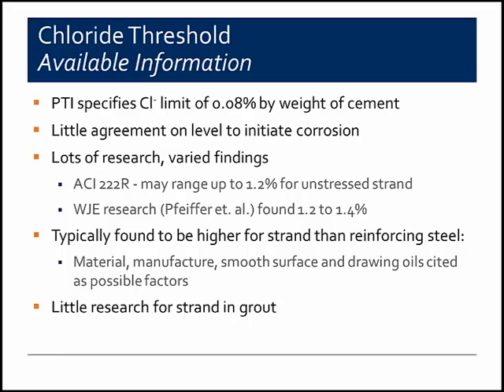In general, the chloride content threshold for strand has been found to be higher than that for reinforcing steel. And although it's not exactly clear why that is, some of the factors that have been cited are the material or the manufacture of the strand, the smooth surface of the strand, possibly the drawing oils. All of those things may contribute to a higher threshold for corrosion. However, there's not nearly as much research for strand in grout as there is for strand in concrete.